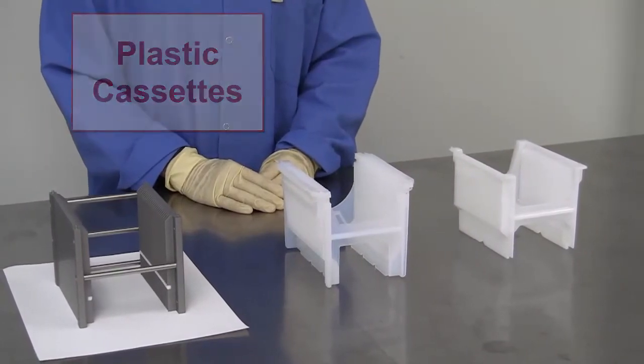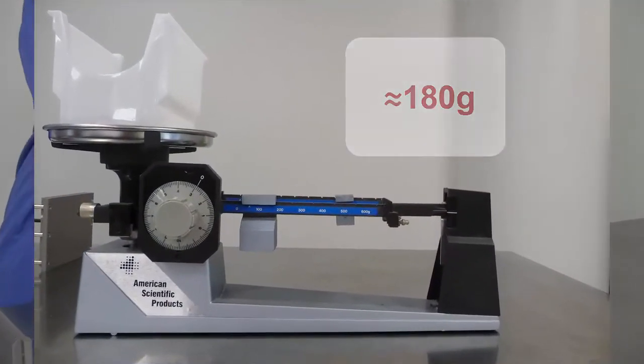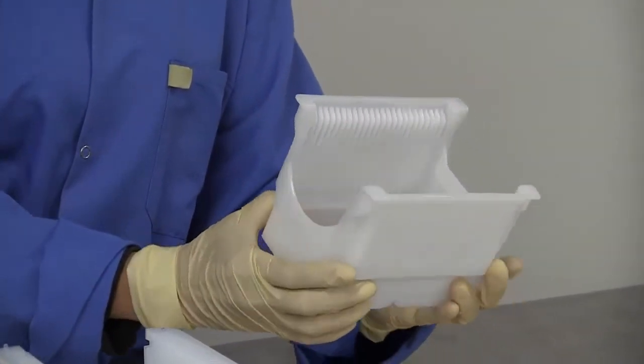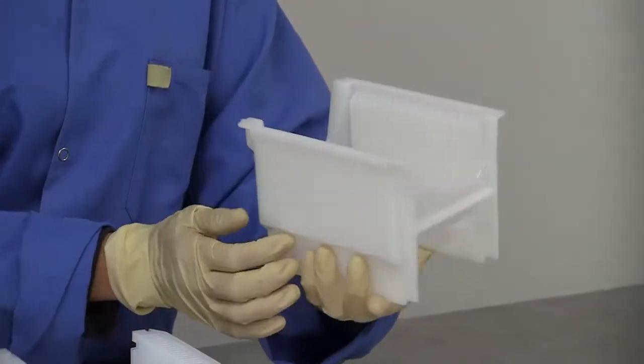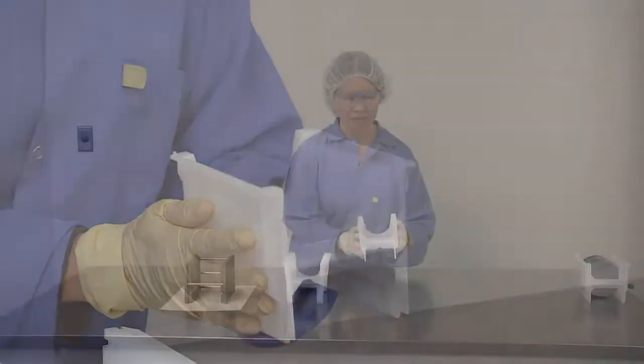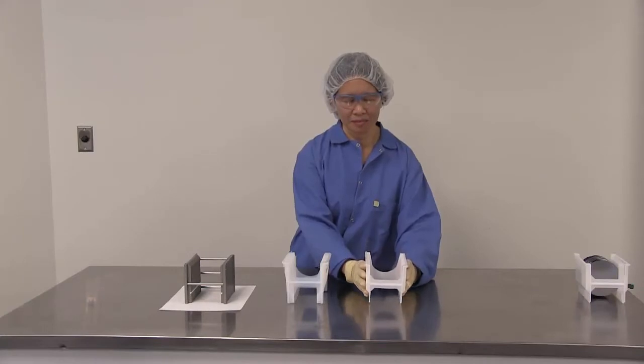Ordinary plastic cassettes are used for storing wafers. These cassettes are lightweight. While convenient for storage, these cassettes are not stable to chemicals, so should not be used in processing. They will also off-gas low molecular weight materials, so wafers that are stored for an extended period of time in plastic cassettes may need to be recleaned.